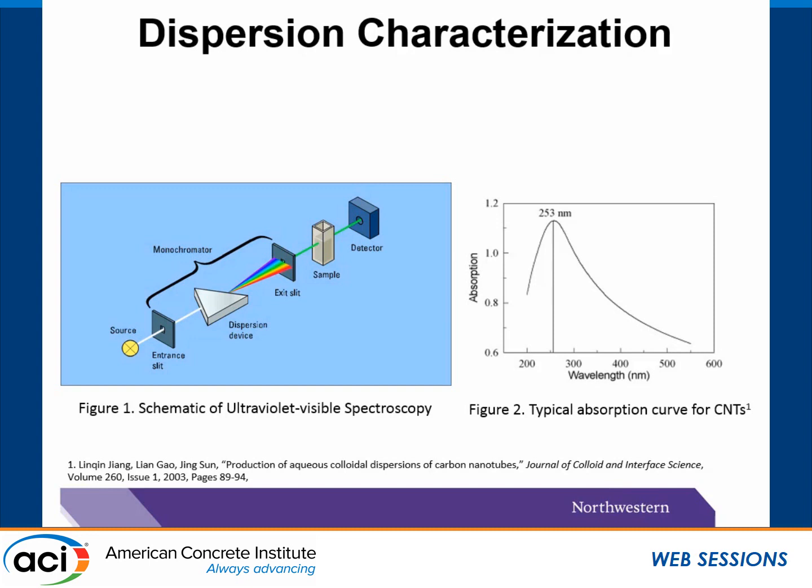ultraviolet-visible spectroscopy. Individual multi-wall carbon nanotubes are active in the UV-Vis region, and show a single peak between 200 and 1200 nanometers, as shown in the figure on the right. Contrary to dispersed CNTs, bundled CNTs are not active within the wavelengths we measured.